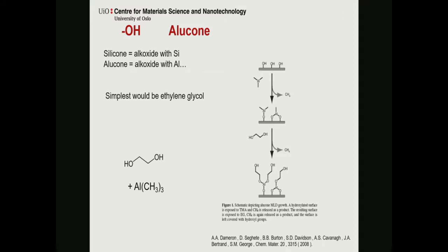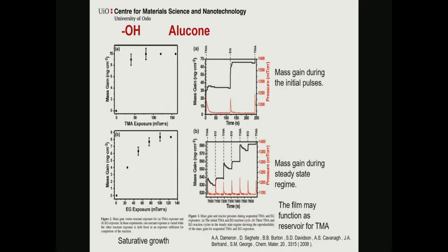You can imagine this structure here, and here shows some of the plethora that you will have. Because when you grow pure aluminium oxide, it is amorphous because it has too much freedom with respect to double bonding or single bonding on the surface. And if you add more possibilities, more complexion here on the anion side, then of course it continues in an amorphous manner. But also during growth, you see some discrepancies.